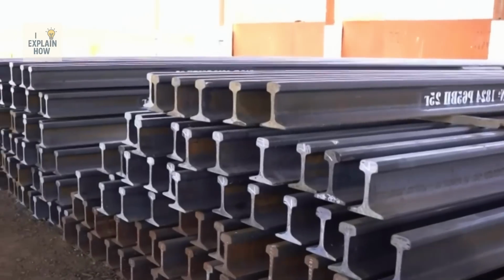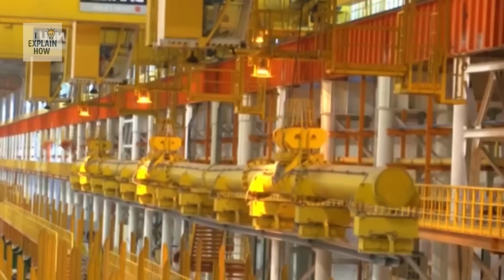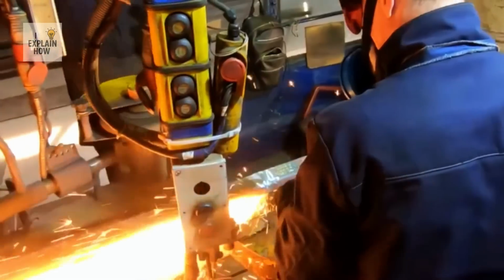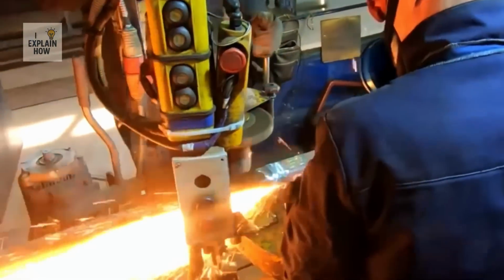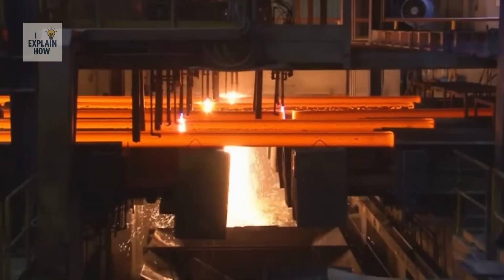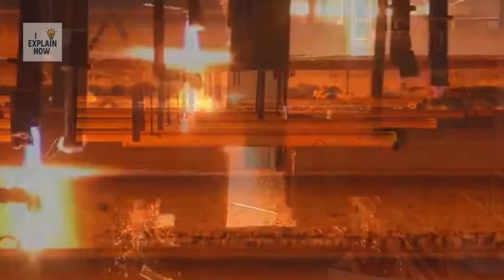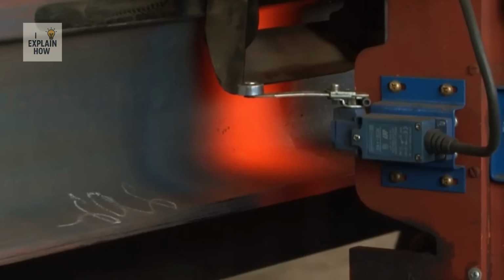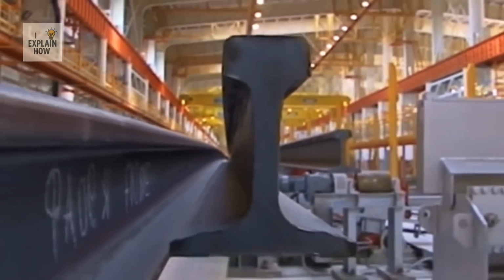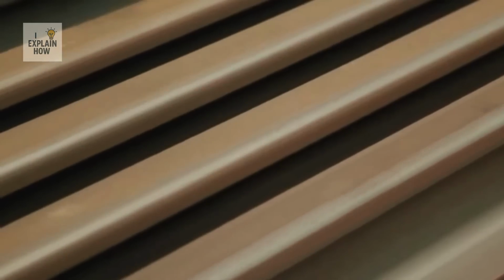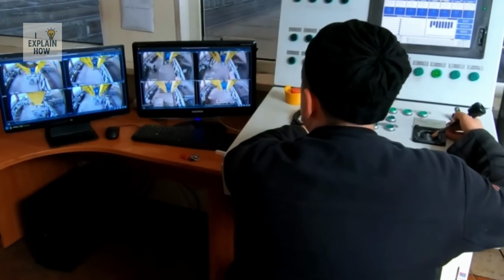Under the intense heat inherited from the rolling process, the steel rails still glow red and contain significant internal stresses. Cooling and heat treatment are the critical steps that stabilize the product's backbone. Immediately after leaving the rolling mills, the rails pass through a high-pressure water spray system, where a dense mist envelopes their entire surface. The speed and volume of the water are tightly controlled to ensure uniform cooling over the entire length, preventing warping or cracking.